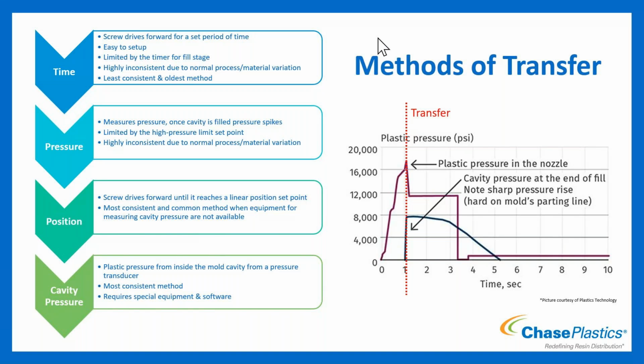There's a couple methods that we can do this, and we've got them listed. These are your standard, most common 4 methods to transfer. Most of your machines will at least give you the top 3 as a standard drop-down menu to select from. And we do have them here in order of accuracy, where transferring by time is not as good as transferring by pressure, which is not as good as transferring by position, which is not as good as transferring by cavity pressure in terms of shot-to-shot repeatability.